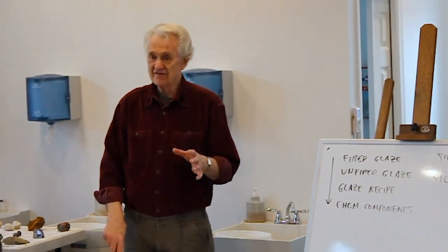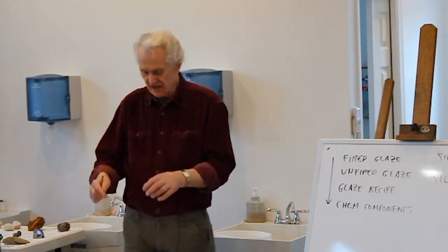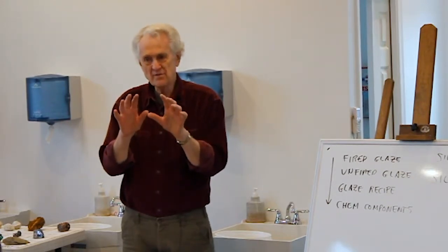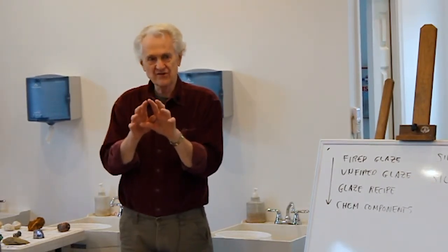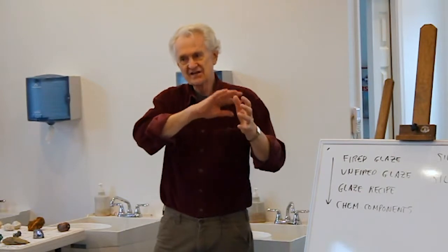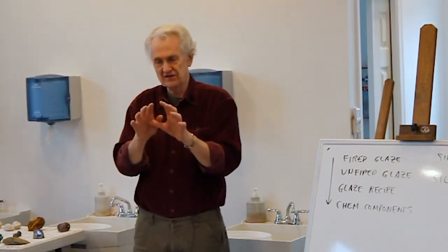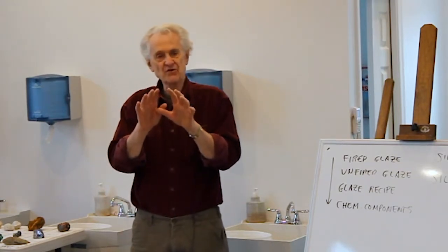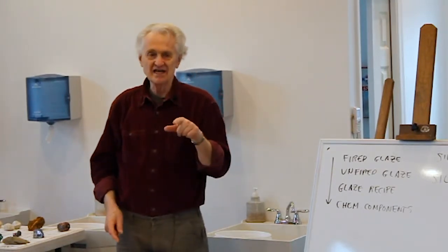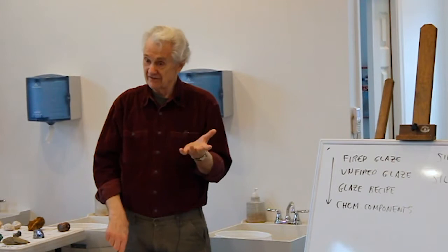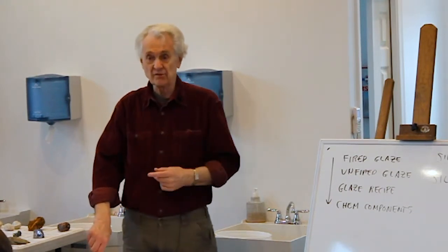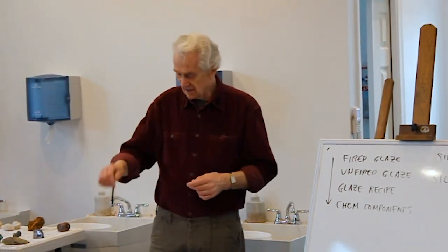So for the base glaze, this is the nice thing about glaze recipes, and we'll talk more about this, but when you combine these ingredients together, there's enough of a latitude. They don't have to be exactly dead on to hit that composition or something close. If you think about how the composition changes and the properties change, it doesn't jump dramatically. It kind of slides gradually. So if I change the composition a little bit and the composition moves over a little bit, the properties move over a little bit, not drastically. So the base glaze doesn't have to be right on the money. As long as it's close, you'll get about the same glaze. Now, for colorants and some of these additives, yeah, you have to be more specific. But in this case, you don't need the decimal points at all. This is just the way somebody went crazy with a calculator.